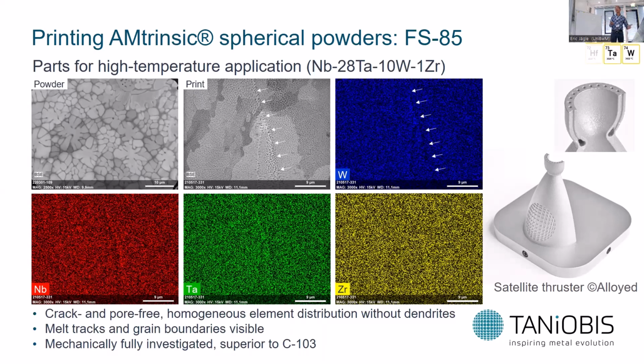This is the dendrite type structure with dendrite phase and interdendrite phase. Surprisingly, remarkably, these structural features completely disappear once the material is printed. And the reason is the different cooling rates. With laser powder fusion, you have much higher cooling rates than during the atomization. Accordingly, the system has no time to separate into these dendrite and interdendrite type phases.